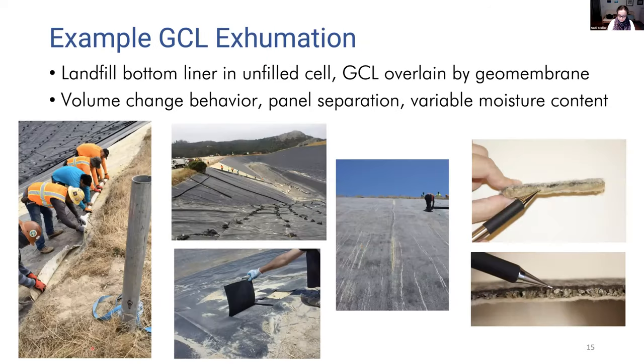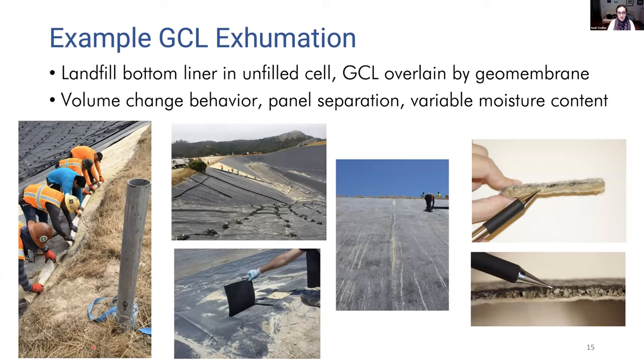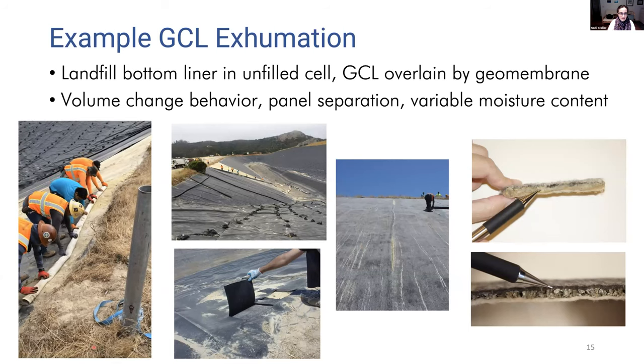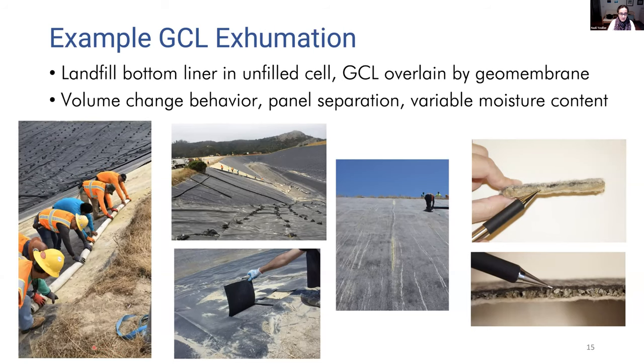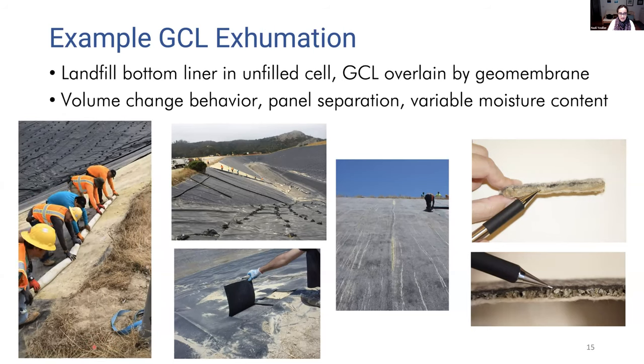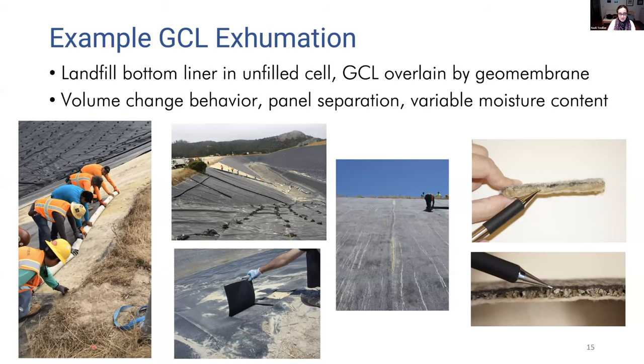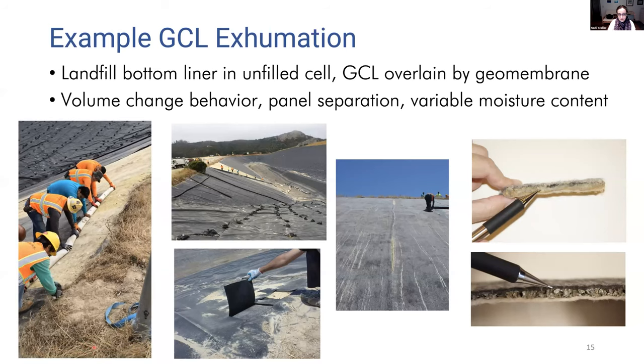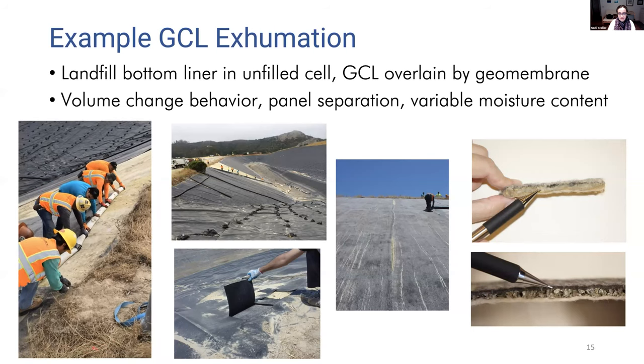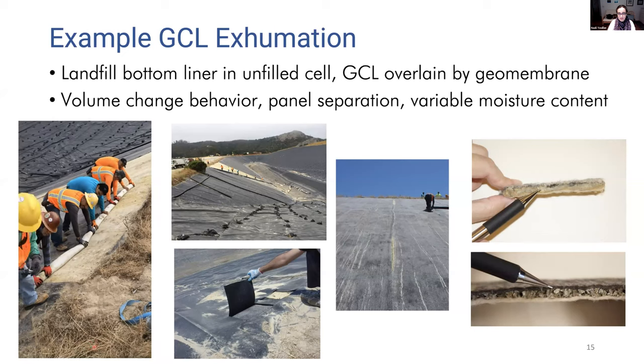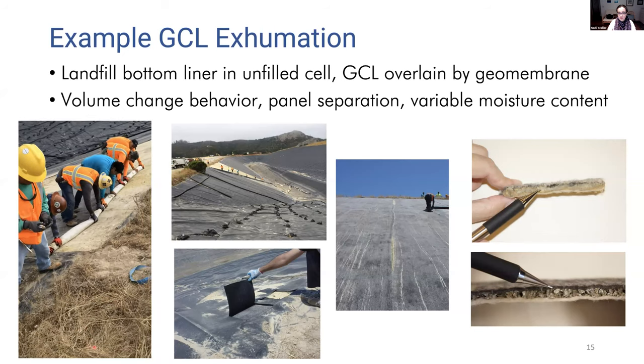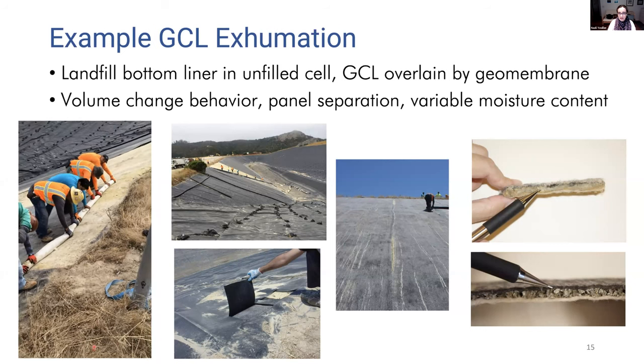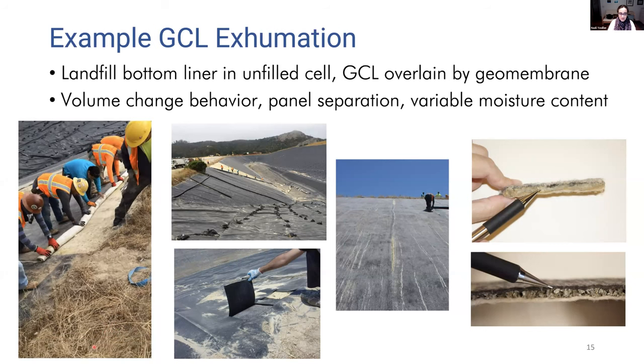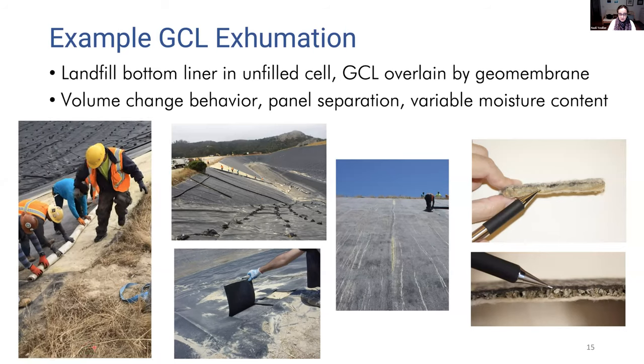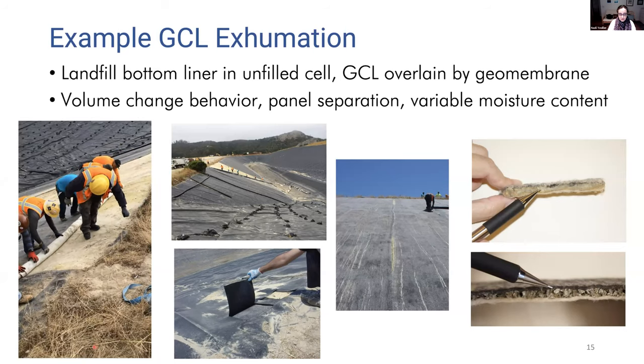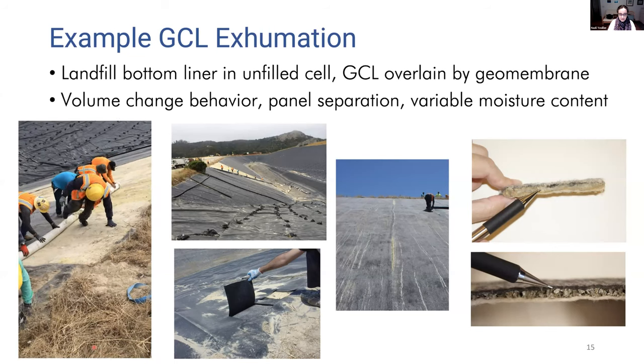I have an example GCL exhumation activity here. This is something that we did locally in our area. This was a landfill bottom liner that was constructed and left exposed to the atmosphere. The cell was never filled for about a 12-year period. In this case, this was a composite liner system, a GCL overlaid by a geomembrane. And at the end of this 12-year period, the landfill operator realized that this material is no longer intact and good to use for a barrier system.